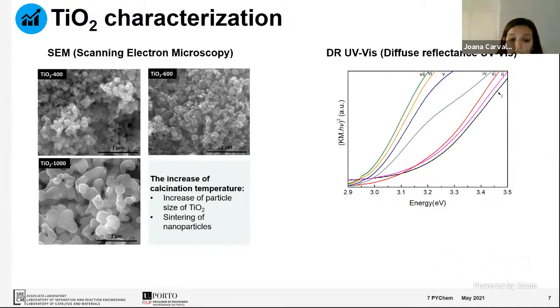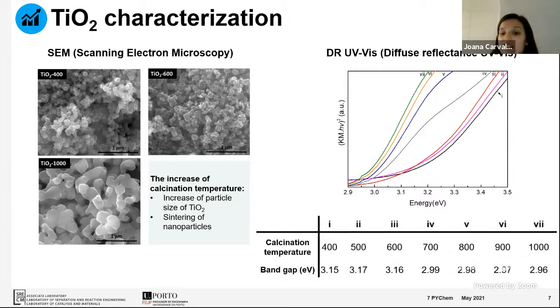In addition to the morphology, the optical properties of the material were also analyzed. In this image is presented the band gap, the Tauc plot of the different materials, and in this table is presented the band gap value of the different materials. Looking at the image, it is possible to see that the material calcined at the lowest temperature, 400 degrees, is the black line. We have a band gap of 3.15.